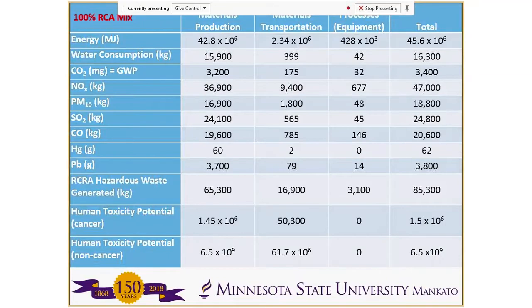So this is a comparison. The first one here is the mix with 100% recycled concrete aggregate. As you can see, many quantities are calculated here: energy consumption for several different processes, emissions, for example, carbon dioxide and particulate matter, and so on. And also towards the bottom, it has hazardous waste and human toxicity potential. When we compare that with conventional concrete, we found that for energy use, it's favorable for the RCA. Some of the emissions are reduced, and particularly down here, the hazardous waste generated and the human toxicity potential are decreased when we use the RCA concrete.